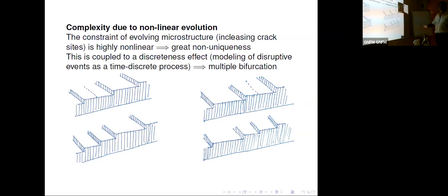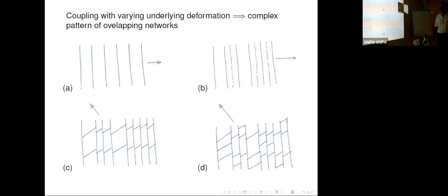So you make some experiments. The first time, even if you take a very simple sample, you get a regular array of cracks, but then as you evolve, at the second critical event, you may have a crack which develops independently on one side. For example, here you can have cracks which are periodically distributed, and then the next crack can appear here or there with the same probability. So you have multiple events in which you can choose, or you can have a non-uniqueness.